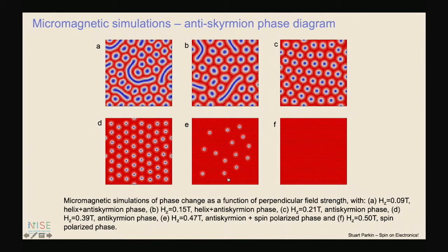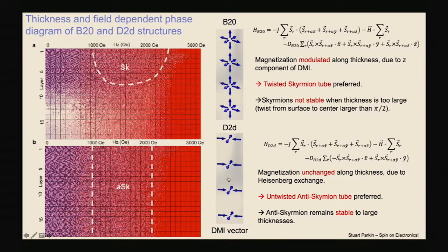So we can actually carry out micromagnetic simulations. And what you see, depending upon the thickness, here this is a certain thickness, as a function of increasing field from the top left to the bottom right. Bottom right is all red, everything is magnetized. Top left you can see both antiskyrmions and the stripes which are representative of the helical system, which can also form. So we can then explore as a function of thickness from simulations what we expect to see.